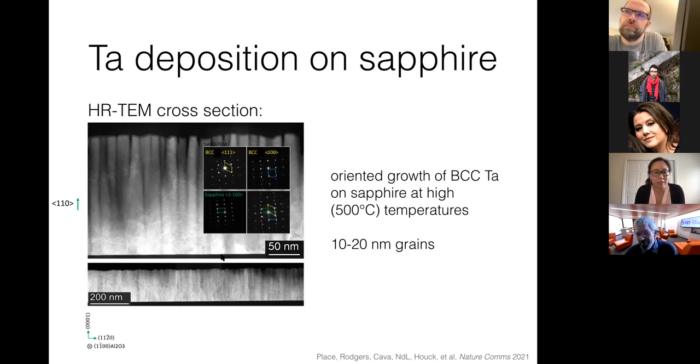We just can't write down any other model, but you get them really ubiquitously if you just do high temperature annealing and then acid cleaning, which is perchloric, nitric, and sulfuric. But you really just get them. There's no special chemistry to get them. You just get them every time you have a disordered surface.